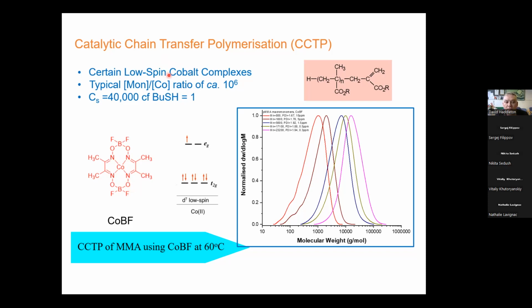We're using this in a very similar way to vitamin B12. A low spin cobalt complex, we're using it as a chain transfer agent to replace a mercaptan, and the monomer to cobalt ratio is 1 million or more. That means its chain transfer coefficient is about 40 to 50,000, whereas a mercaptan will be about 1. For those of you not familiar with free radical polymerization, a mercaptan is regarded as one of the most efficient chain transfer agents there is, and they're used commercially all the time. The chain transfer coefficient of, say, benzene will be 10 to the minus 6. So we've got a compound here that's 4 orders of magnitude better than the best chain transfer agents. So when we use that, we need 4 orders of magnitude less in grams or moles to get the same effect.